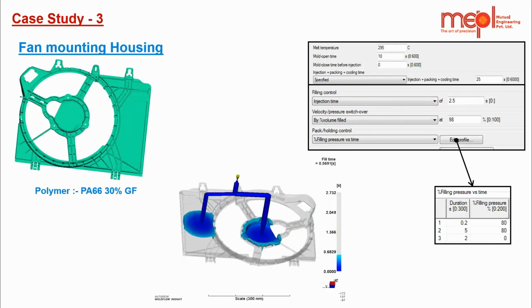This is our case study 3. It's a fan mounting housing, and the polymer used for this part is PA66 30% glass filled. The process parameters are as shown for the fill-flow-warp analysis, and you can see the filling pattern of this part. The challenge was to achieve the dimensional stability of the part.